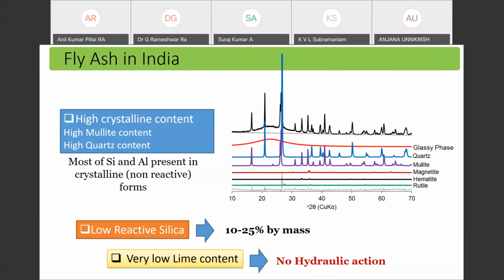And we found that, unfortunately, our fly ashes have low reactive silica in them. It's only 10 to 25% by mass of the fly ash. So if I take 1 kg of fly ash, only about 250 grams, or sometimes as low as 100 grams of that total fly ash is present in reactive silica form, which I can then use as cement replacement. And because it has a very low lime content, it does not have any hydraulic action, which means if I mix fly ash with water, it is not going to react because there's no calcium present in it.